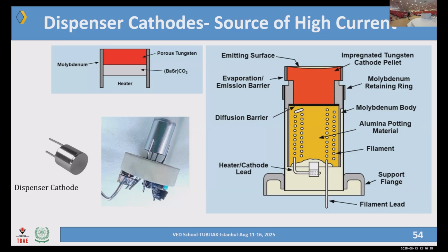And then we have a reservoir which is filled with barium, strontium carbonates. In fact, it's not the complete recipe. I will give you the reference of the book. You can go through the data. It's a standard thing. It's barium carbonate, calcium carbonate, aluminum oxide, mixed in certain ratios and put in this reservoir.